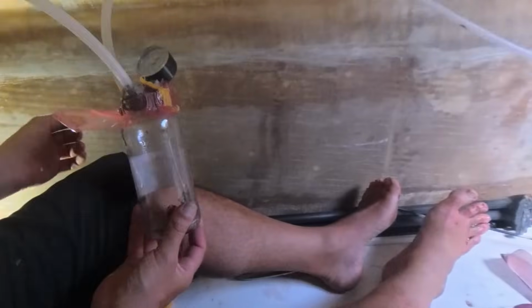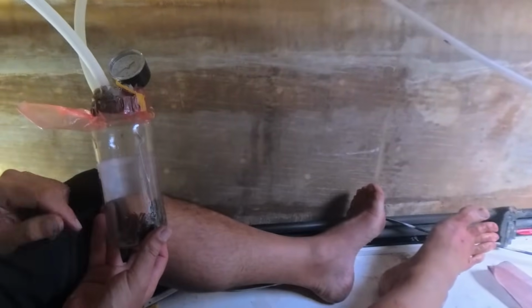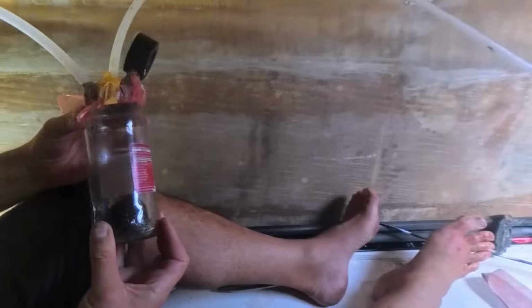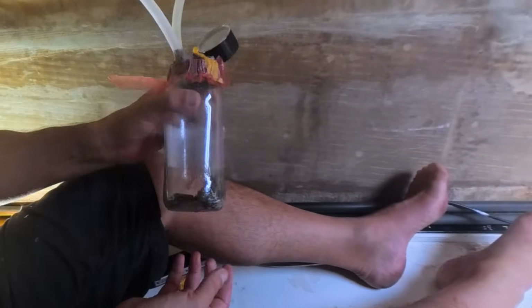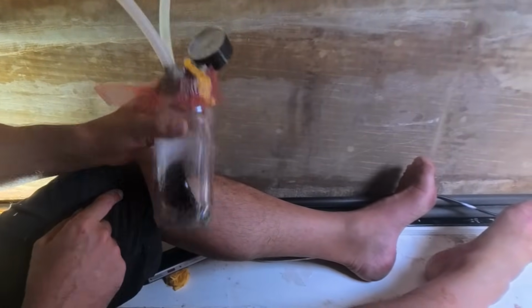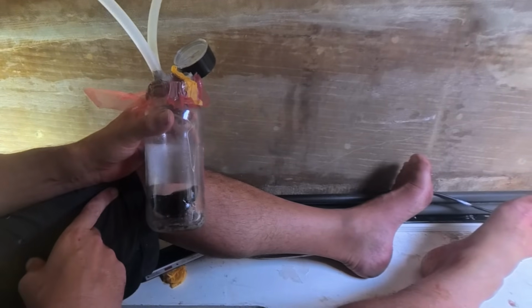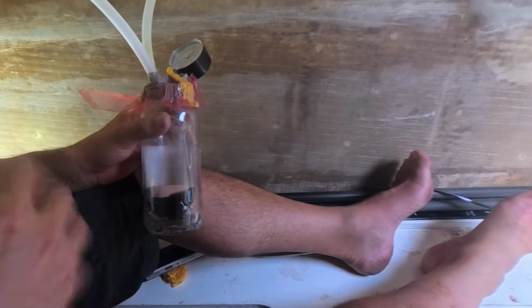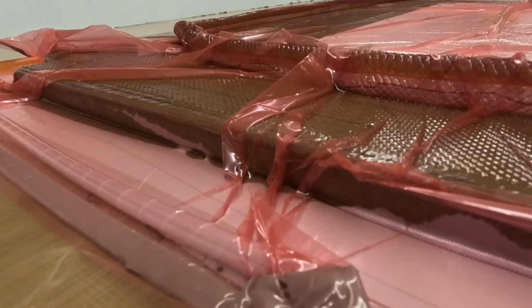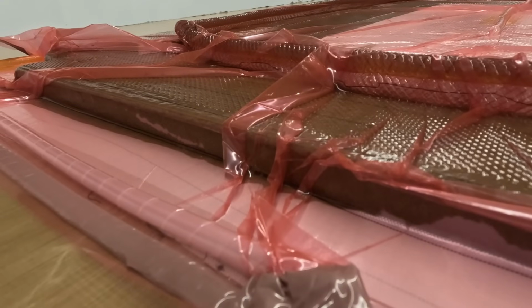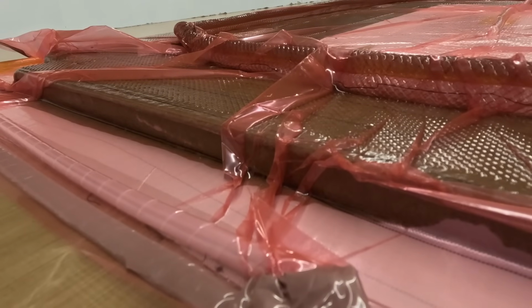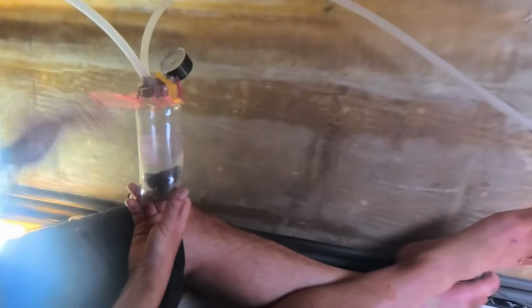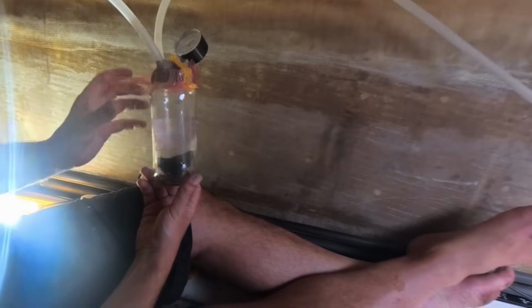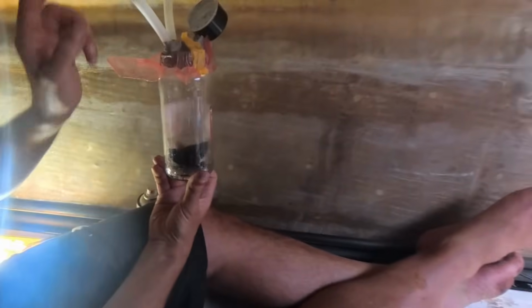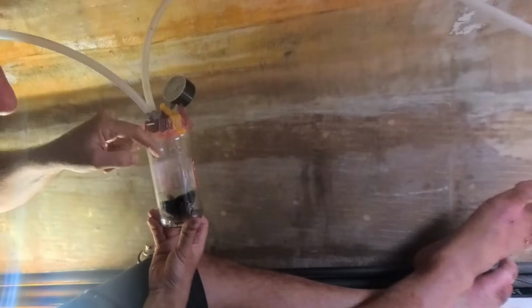Alright, this thing, super highly technical piece of equipment, this. It's my olive jar. That's not olive, is it? Oh, maybe chickpeas. So it's just a glass jar, and you can see there's actually a bit of resin rattling around in there from when I didn't totally cock up an infusion. If you infuse something and you have a racetrack or you let the resin run too long, you end up with resin coming into your vacuum line. And what happens is the resin will drip out of the hole here into the jar.